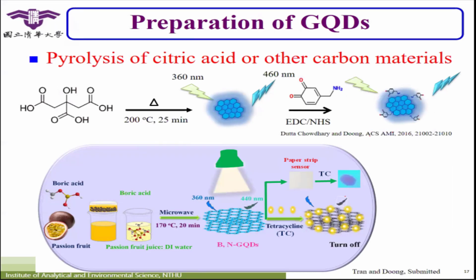So how to prepare graphene quantum dots? That's quite simple. You can use the top-down method. That means when you have your graphene family, reduced graphene oxide or others, you can use physical methods to grind and chop them into quantum dots. That's the physical method from the top down. And from the bottom up, you can use chemicals. For me, I prefer the chemical method. With the chemical method, we can fabricate quite nice and uniform particle sizes.